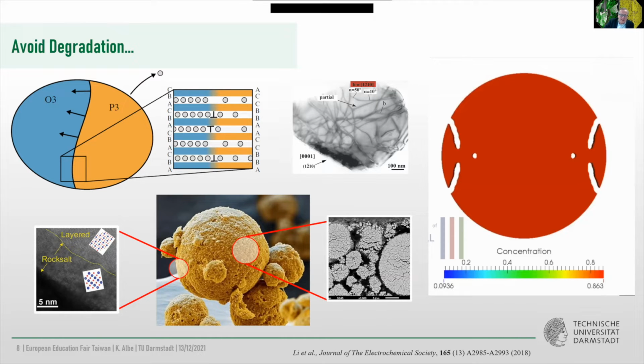First of all, one can work on methods to make them last longer. I mean, as you know from your laptop or from your mobile phone, after a couple of years, batteries are degraded. So, just work on the lifetime of the system. And one issue I will mention later is that in these interlayer systems, like lithium cobalt oxide, essentially you intercalate and de-intercalate the lithium. And when you do that, and this is what you see on the schematic, the less lithium you have, the higher is the tendency that the material wants to change the stacking between the transition metal oxide layers. Because the screening effect of the lithium is going away, the system wants to shift planes. And in order to do that, it needs dislocations.